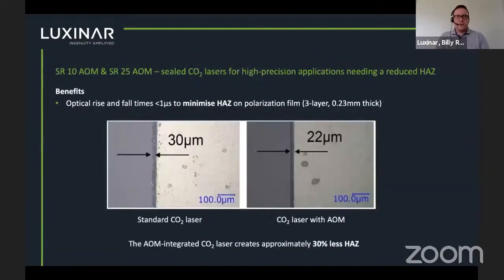So just a quick look at some example applications of material processing using these lasers. So first of all, this is comparing a standard CO2 laser with a CO2 laser with integrated AOM for machining of 3-layer polarization film. So you can see on the right-hand side, the material processing with the CO2 laser with AOM produces approximately 30% less heat-affected zone compared to a standard CO2 laser with longer rise and fall time pulses.